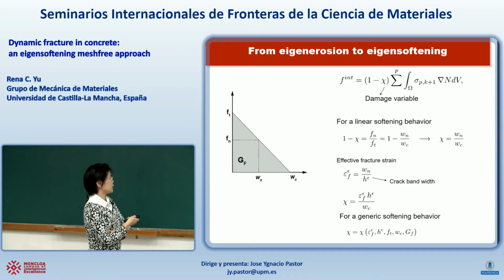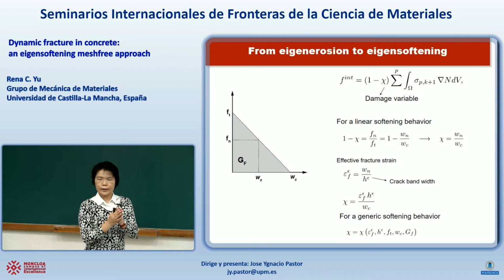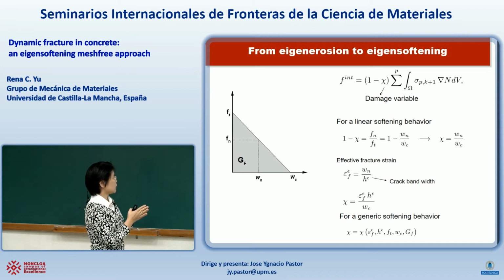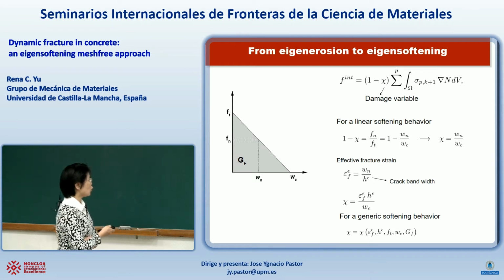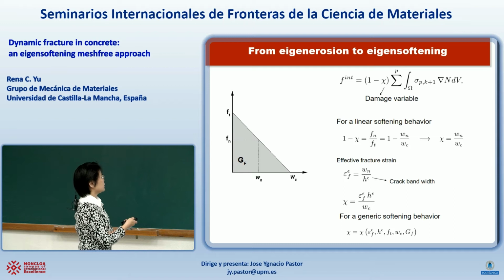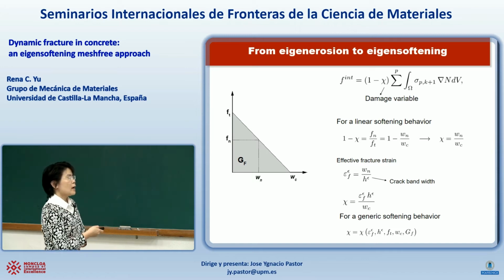What you see here is that in concrete, I'm not sure if everyone knows, when the cracks start to form, it opens gradually. So it does not go to zero right away. It gradually softens until our critical opening. This is the case for linear softening behavior, and the shaded area is the fracture energy.